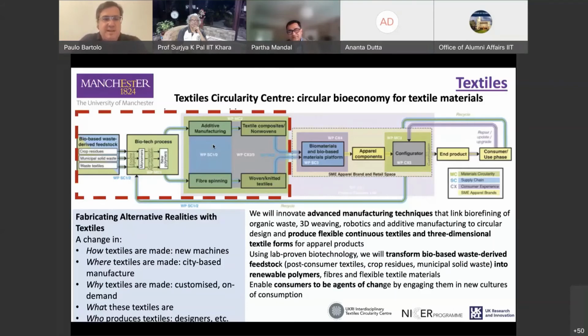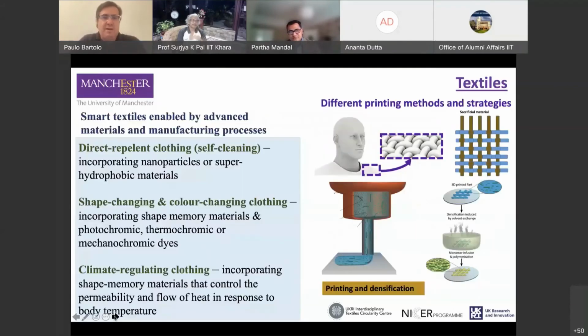As I mentioned, the project started in January. We are focusing right now on bacterial cellulose. There are multiple possibilities to print bacterial cellulose. One is mixing bacterial cellulose with a biodegradable polymer and printing the composite using normal extrusion, or preparing a bio-ink, a bacterial cellulose ink, and then we can use 2 different routes. One is to print the ink in a coagulation medium, using, for example, ionic liquids, or printing the ink in a solvent for densification, so as to increase the mechanical properties, and after that finalize the printing process through a final cross-linking mechanism by using UV radiation, for example.